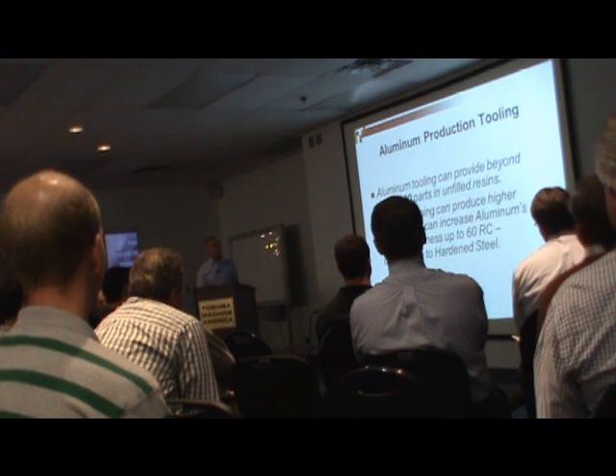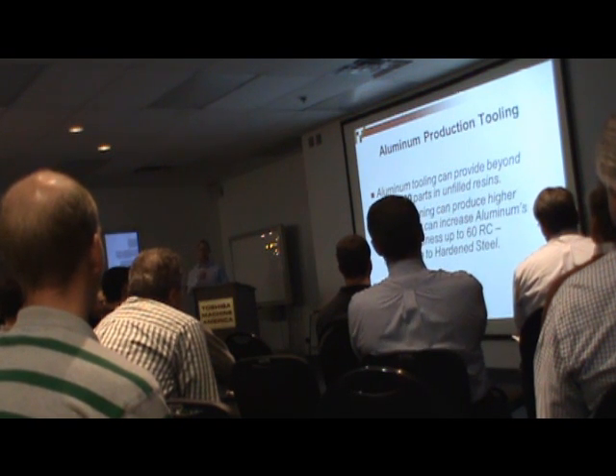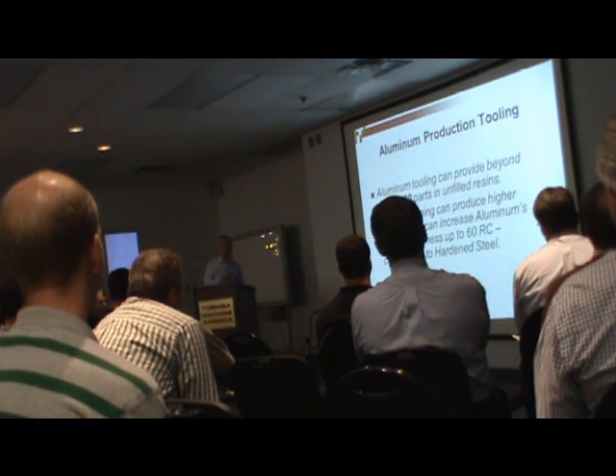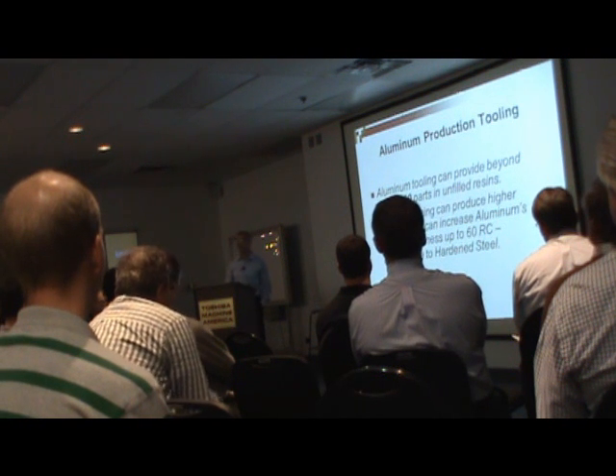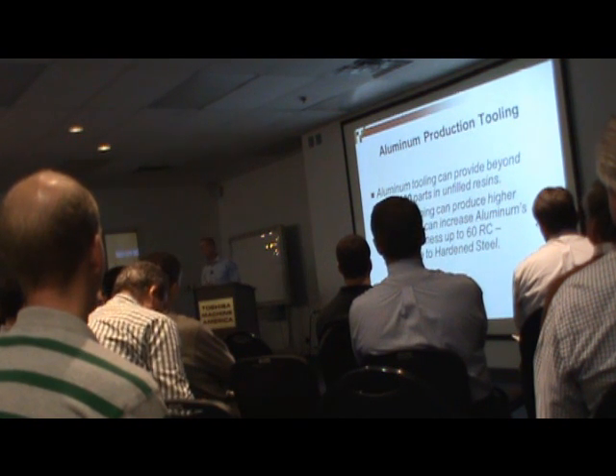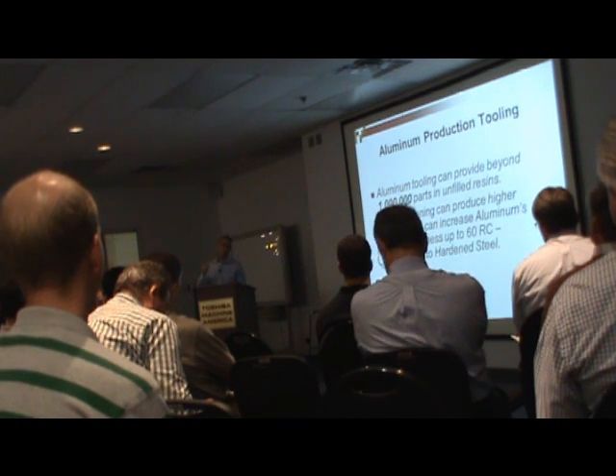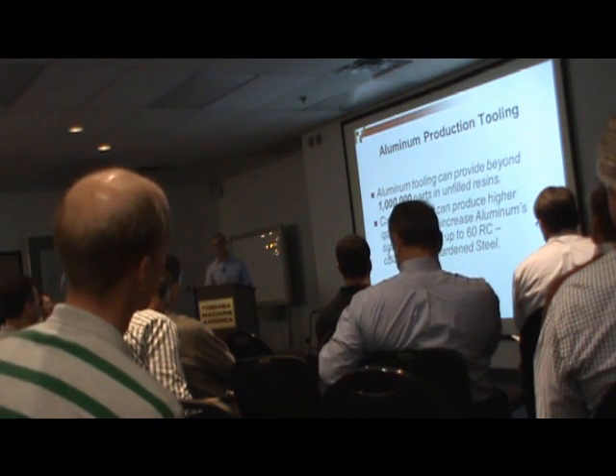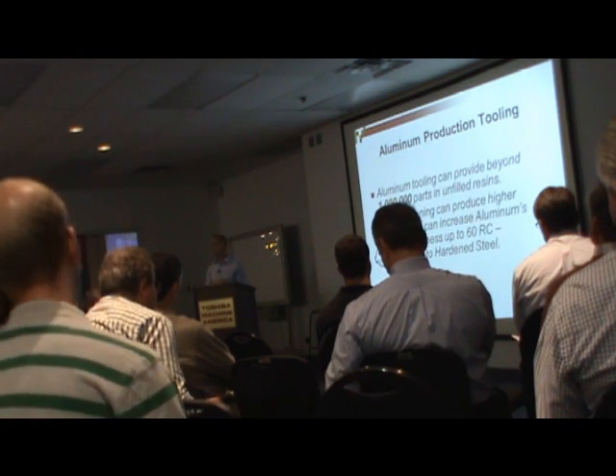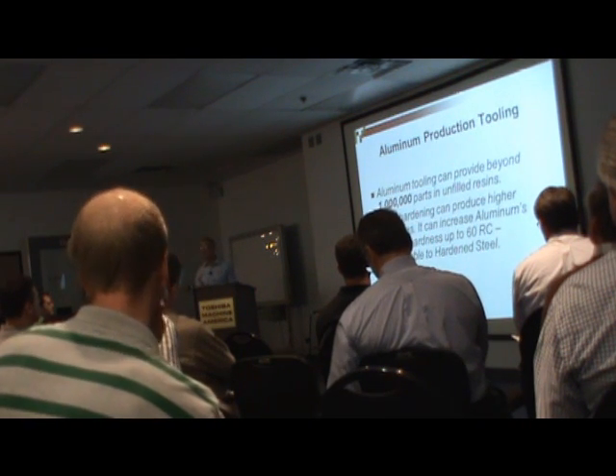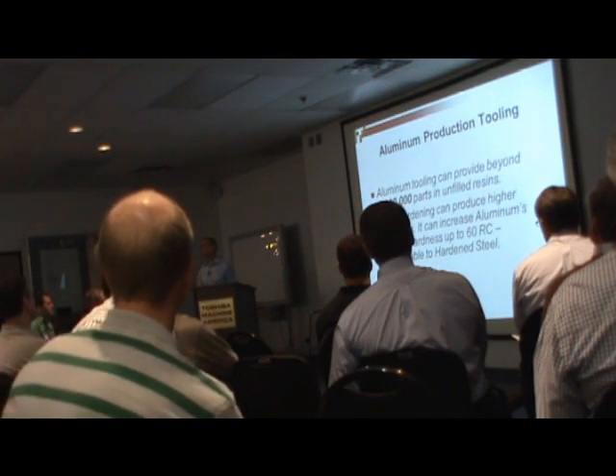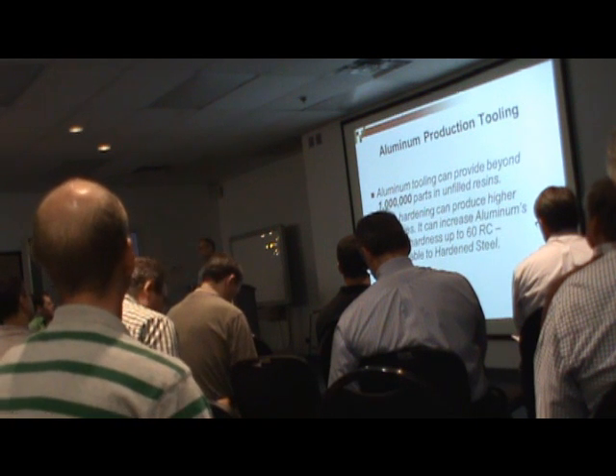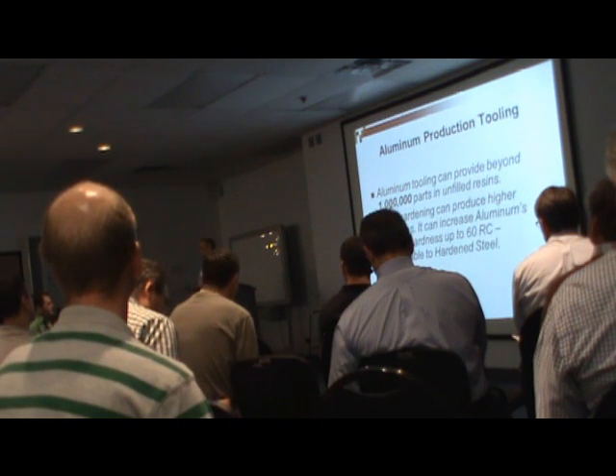We've seen that we can provide well over 1 million parts. Again, keep in mind you have case hardening that takes a surface hardness up to over 60 Rockwell. We prefer not to go over 60. We prefer to go around 54 to 56. It's a buildup. It does not impregnate into it. It's a buildup for us of about 2 to 3 tenths. We monitor it. How do we do that? We monitor it visibly. We also do it by our checks. We do with temp indicator. We check our wear.